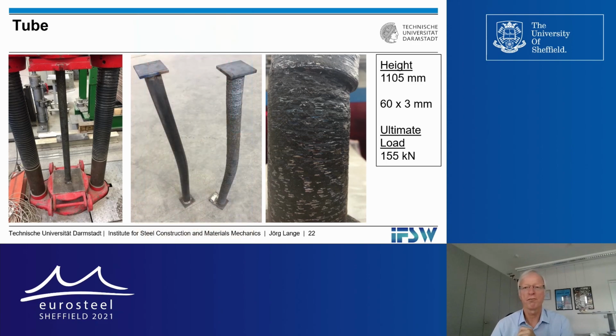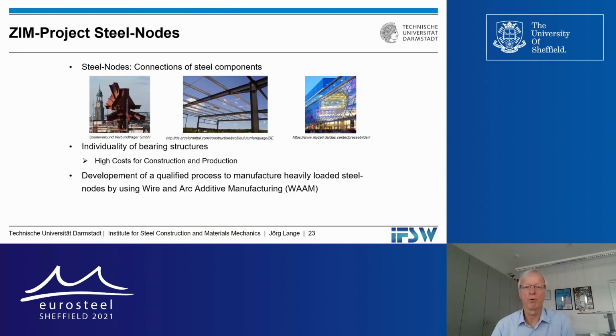Even if in this way you can print up to 9 or 10 kilograms per hour, you need much time, and you just get an advantage if you print such an extraordinary geometry as the MX3D bridge that was printed in Amsterdam, or some special arch-shaped column. The ultimate load was nearly the same. We expected from the additive manufacturing, with all the heat-induced eigenstresses, that the additive manufactured column might have a lower ultimate load, but it had approximately the same as a hot rolled column. So that was a very successful project, but as I said, that's only interesting for strange shapes, odd shapes that we don't get with hot rolled or cold bent products.